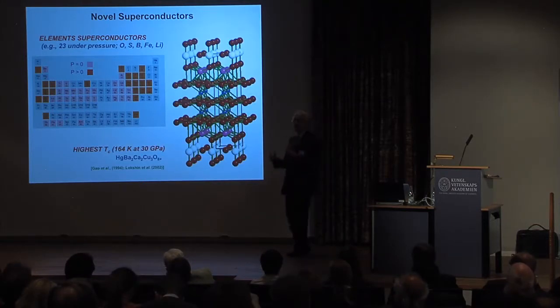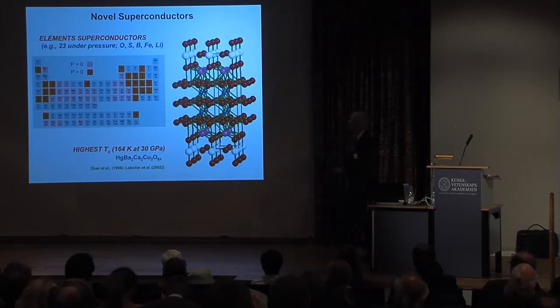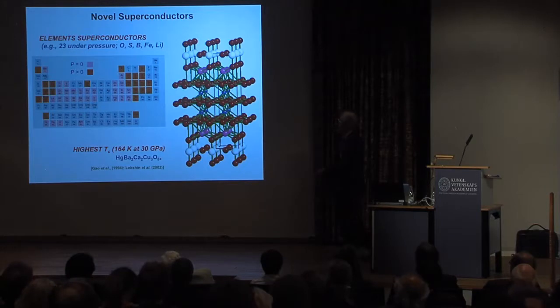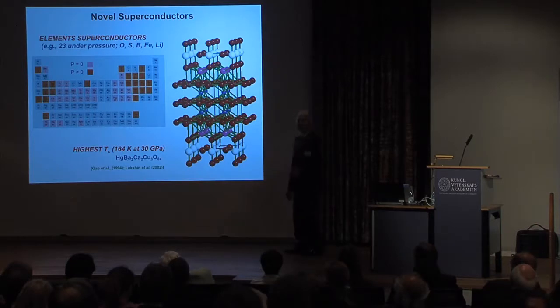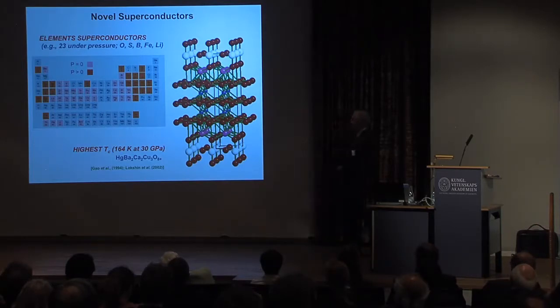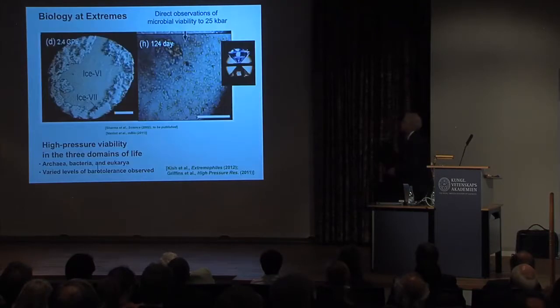In addition, the highest TCs on record, the highest temperature superconductivity, is found in this particular cuprate, this mercury-barium-calcium cuprate, which has a TC of 164 Kelvin, which remains the highest to date, and that's a measurement at 30 gigapascals, or 300 kilobars.